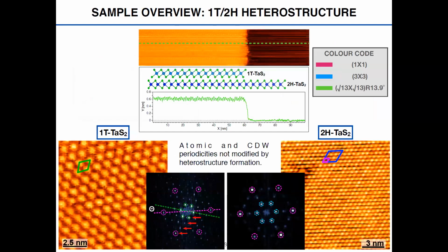We are able to identify this heterostructure by means of single layer step edges, like the one shown here. So the area to the right is the 2H crystal, and the area to the left here is this 1T area. Then more or less the height of the single layer step is the one expected, so 0.6 nanometers. The corrugation you're seeing here is not due to the atomic corrugation, but due to the corrugation of the charge density wave. This is the corrugation of the 1T charge density wave that is much more corrugated than the 3x3 of the 2H layer.